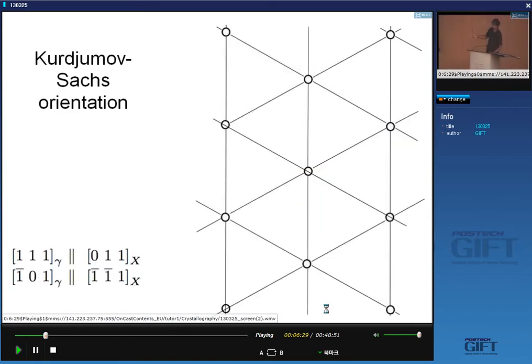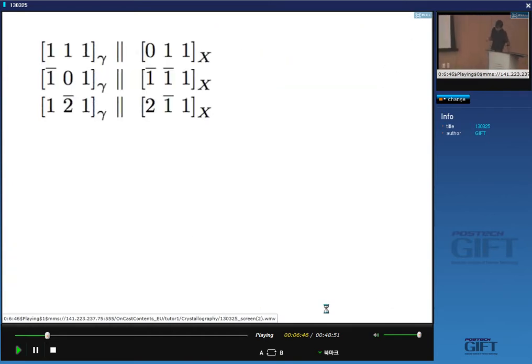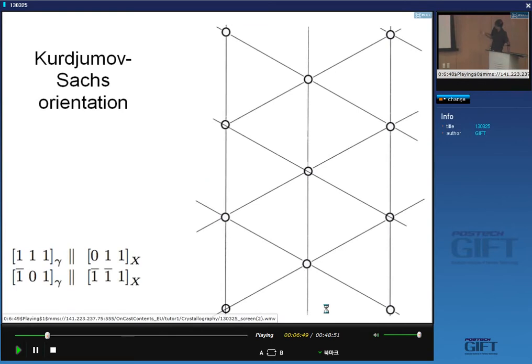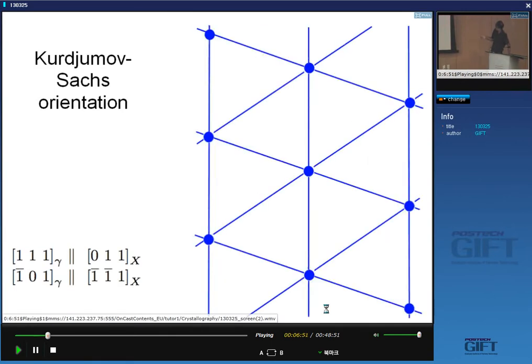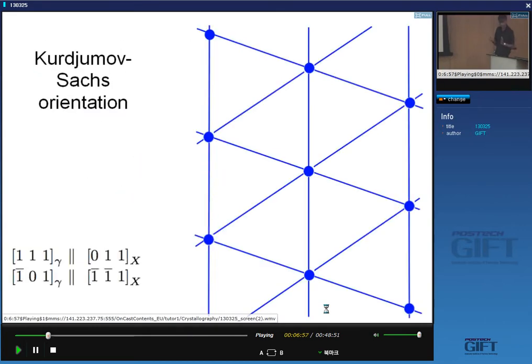Okay, so here we are. I've got the 111 plane of austenite, the close-packed plane, and I'm going to superimpose the ferrite plane so that the close-packed direction of ferrite is exactly parallel to the close-packed direction in the close-packed plane of austenite, and this is what the ferrite will look like. It's a squashed hexagon, and actually they should be superimposing, and they don't seem to be transparent.